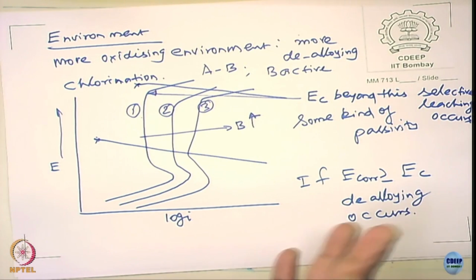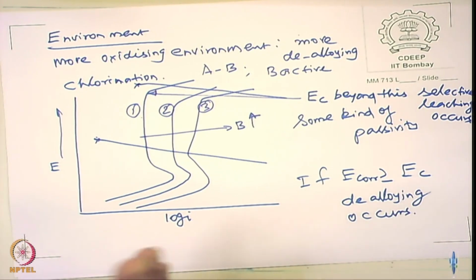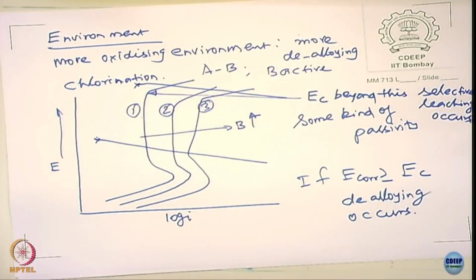Yeah, it is not pitting here. You don't see a pit here in this case. That's why in the copper-zinc system and copper-nickel system, you don't get a pit at all. If you observe the surface here, you will see the surface is enriched more with copper, because zinc is just getting out of it. Similarly in copper-nickel, nickel comes out of solution.